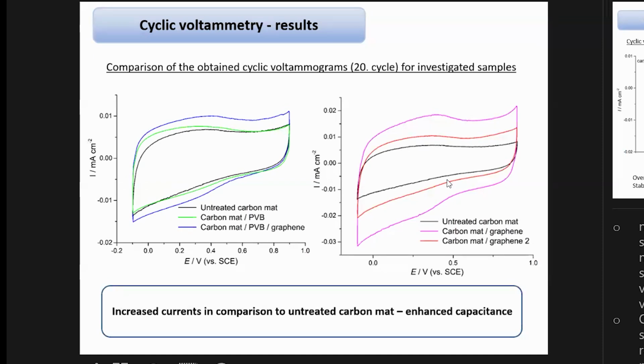And on the right side, we have also compared 2 different carbon mats covered with graphene in 2 different ways. What is the difference between the first carbon mat and the second? The second one was coated 2 times, like a double amount of our functional coating was placed on the sample. So this means that with our new graphene-modified polyvinyl butyral coating, we are obtaining increased currents in comparison to the untreated carbon mat, which means enhanced capacitance.